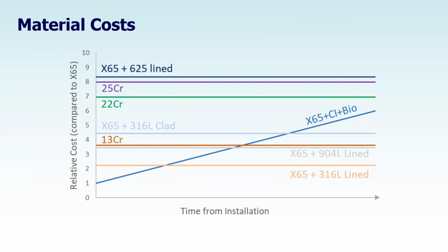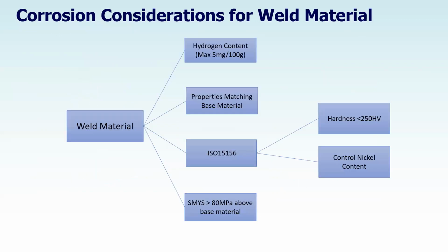And so we may get a situation where a carbon steel clad or pure CRA option becomes the most viable option. Once we've chosen our pipe material, we need to make considerations for welding consumables. In general, we want the mechanical properties to match those of the base material, whilst having a higher yield strength. And specific considerations need to be made for the presence of H2S as per ISO 15156 to control hardness and nickel content.